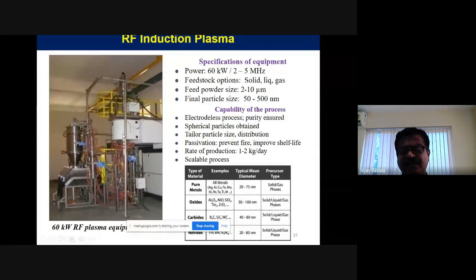immediately, because of the high temperature, the material becomes vapor, and that vapor is quenched by passing argon gas, and you get a metal; if you pass oxygen, you get an oxide, and if you pass nitrogen, you get a nitride. So this is what you can always play with to get the materials. And these are all pushed by the gas and come into this hopper, where you can collect them in the glove box.